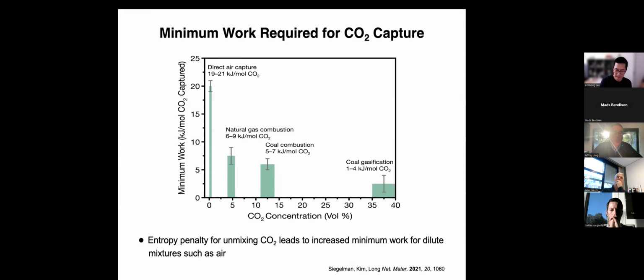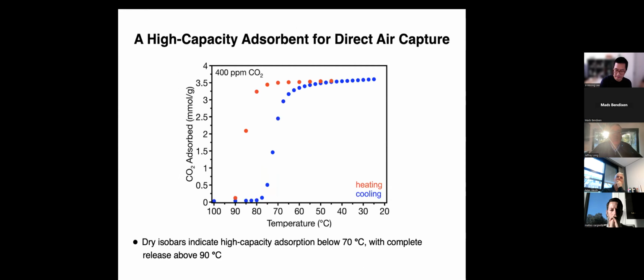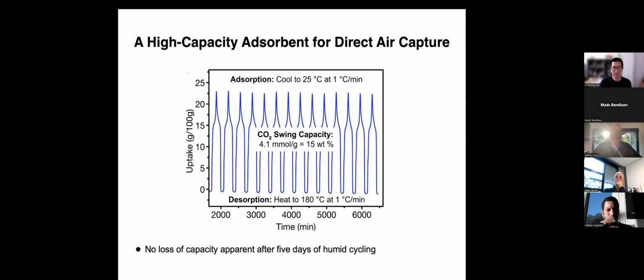And so this is a much bigger challenge, but we've seen that we can see very good performance from materials of this type. This is showing isobars under 400 ppm of CO2, showing, you see it again, the step indicating that cooperative CO2 process. The blue data is upon cooling. So at low temperatures, you're having a high capacity for CO2 removal from air. And then when you warm, you can see even by 90 degrees, with a vacuum, you've pulled off the CO2. These can cycle at high capacity under various conditions that we're now testing.